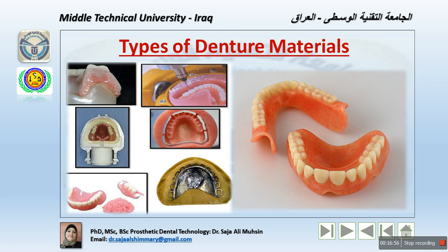In terms of porosity, there are two types of porosity recognized with the polymeric or with the resin acrylic denture teeth. These are the contraction porosity and the gaseous porosity. And the difference between them is, for example, the contraction porosity occurs when the monomer contracts by some 20% of its volume during processing, while the gaseous porosity occurs due to the exothermic reaction of the polymerization, which could make the temperature of the resin rise above 100 centigrade, which is the boiling temperature.